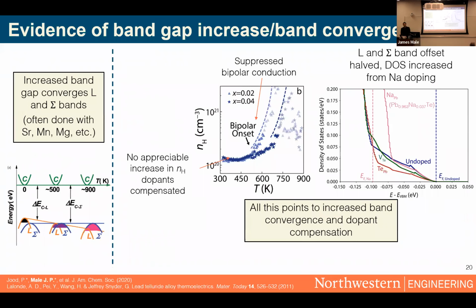Another effect we saw from this enhanced solubility was in the band structure of lead telluride. To give a brief introduction to lead telluride's electronic bands, the conduction band typically consists of what we consider to be essentially one band. But if you look at the valence band, there are actually two bands that might be contributing to transport: both a lighter L band and a heavier sigma band.